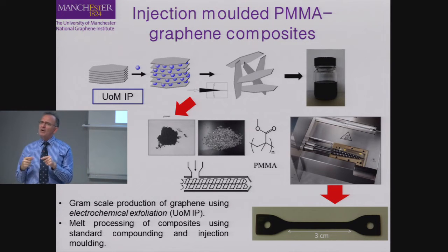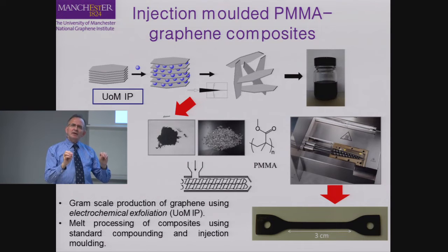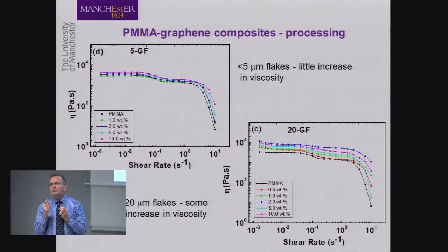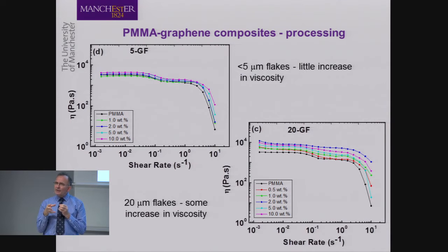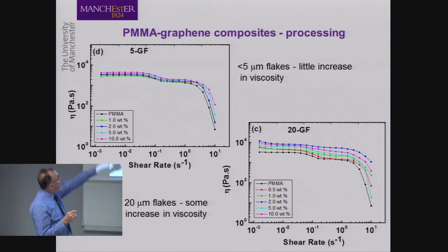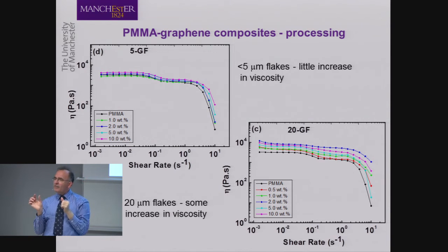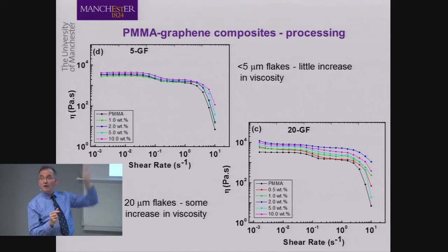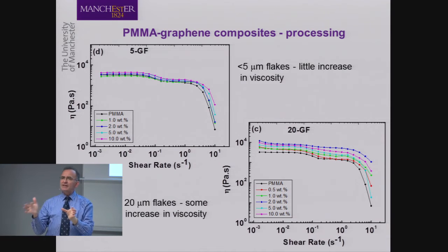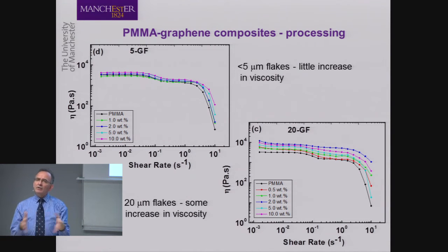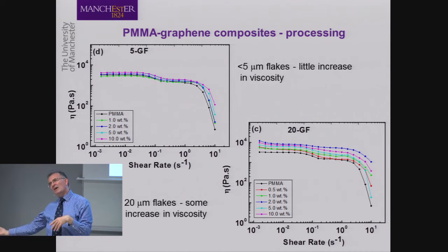But it's to demonstrate how you can mix it, because the mixing and distribution of graphene has a huge impact on the properties that you will achieve in your final product. And also you want to demonstrate that as you increase the amount of graphene, you don't alter viscosity. And we can see in the top left graph, if we have the 5 micrometer graphene flakes, as we increase the amount of graphene from 1% to 10% by weight, we don't alter the viscosity. If our graphene is of a larger size, 20 micron graphene flakes, then we can see as you increase the amount of graphene in your polymer, you change the viscosity, which means it's going to have an effect on your manufacturing process.